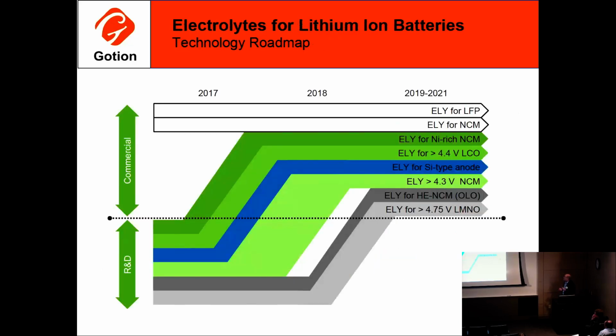Along with that, my area of contribution to Gotion is the electrolyte development, so you'll hear a lot about electrolyte things in the next couple of slides. That roadmap matches as well. You have the electrolyte for LFP and NCM. It's pretty standard material. It needs a little bit of tweaking, but it's pretty good. But then as you go higher up, you need electrolytes for high nickel NCM materials, then the high voltage NCM materials, and then ultimately the high energy NCM cathode materials and the LMNO high voltage spinel type materials. So it matches up, which it should.